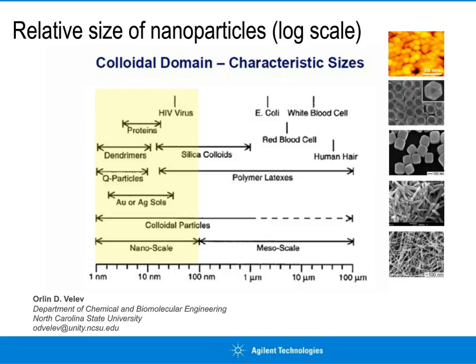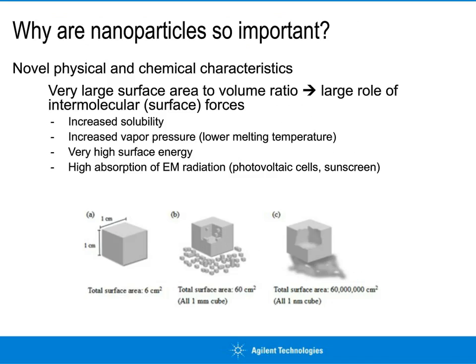So why are they so important? Well, it turns out that nanoparticles have very novel physical and chemical characteristics that are based on a lot more than just their elemental composition. It turns out that their very large surface area to volume ratio imparts a large role of intermolecular or surface forces, and that increases the solubility significantly.